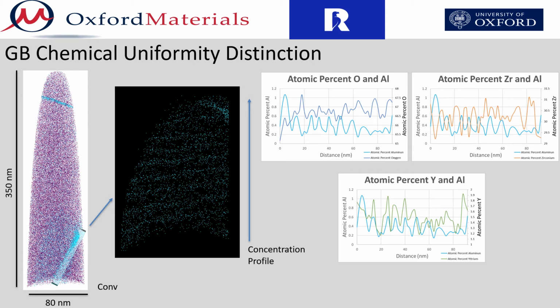Only a few of these boundaries have been found in the datasets analyzed, and once again no connection with sintering type has become evident. These regions of oscillating segregation could be the result of structural anisotropy, such as grain boundary dislocations. However, this structural information is not discernible from the collected APT data.